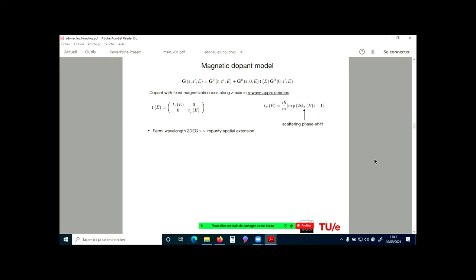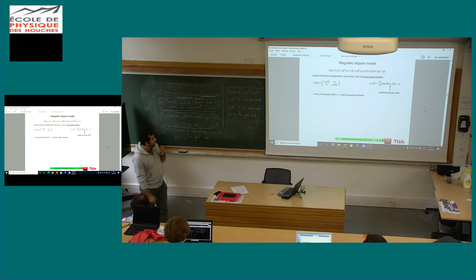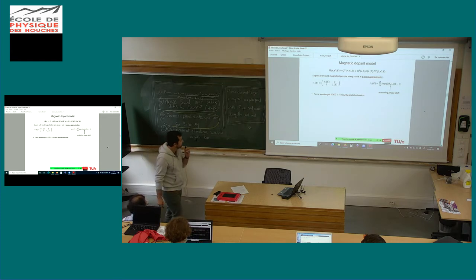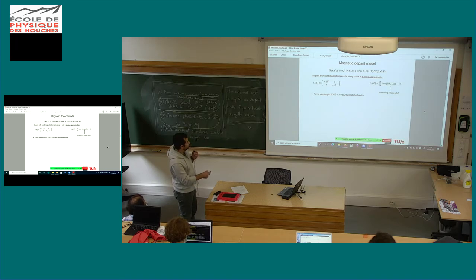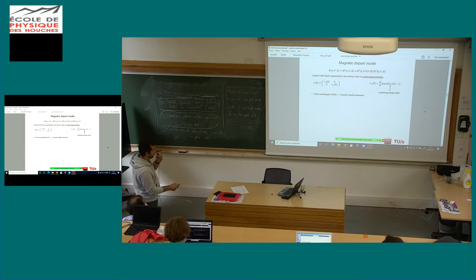So going a little bit further, I also developed a very simple magnetic dopant model, which I solved by the T-matrix formalism, and I make a lot of approximations here. Basically, I'm just assuming a fixed magnetization along the z-axis, perpendicular to the quantum well, and I'm assuming isotropic scattering, so it's a strong approximation. And neglecting also the spin-orbit at the site of the impurity,